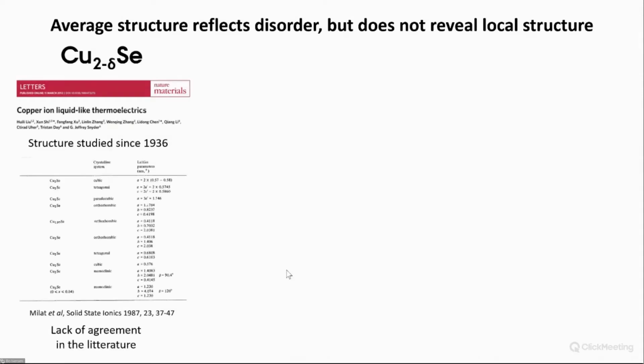My first example here is copper selenide, because I do a lot of thermoelectrics, so a lot of examples will come from thermoelectrics. And copper selenide was almost going to space, right? It was really heavily studied by NASA in the 60s. But the problem is it has very high ionic conductivity, so it deteriorates, and it was never chosen for the missions. But it has been very heavily studied, basically. And if you look at the crystal structures of copper selenide, you can pick any space group or any crystal system you want.